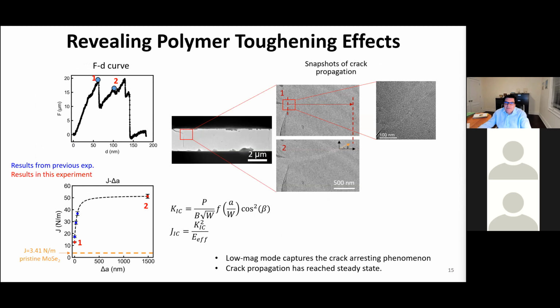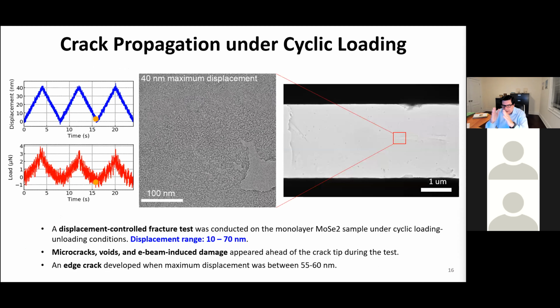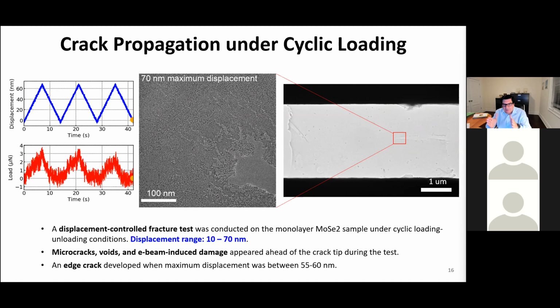We did another experiment that we thought it would be nice to look at. Since the MEMS devices have a lot of control in displacement and prescribed displacement, we could have a load this time that instead of being monotonic, it could be cyclic with the amplitude that we change from, let's say, far field 10 nanometer displacement, 30 nanometers, 50 nanometers, 70, but cycling with the hope that we could develop a sharper crack, like a fatigue type of crack.